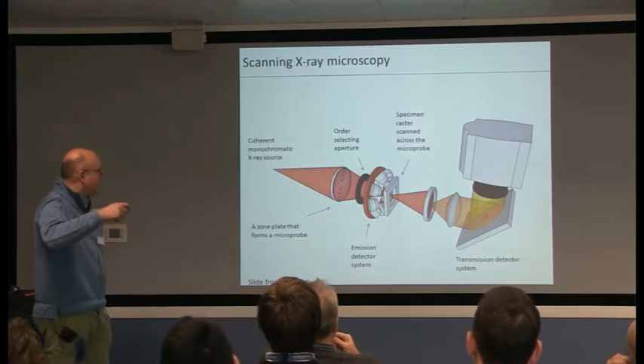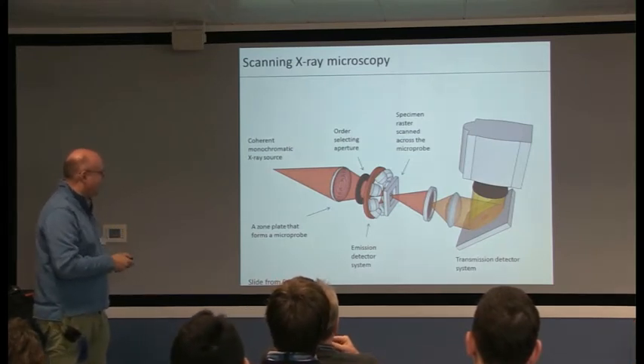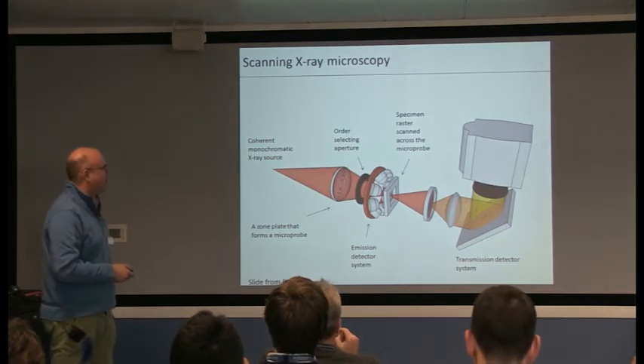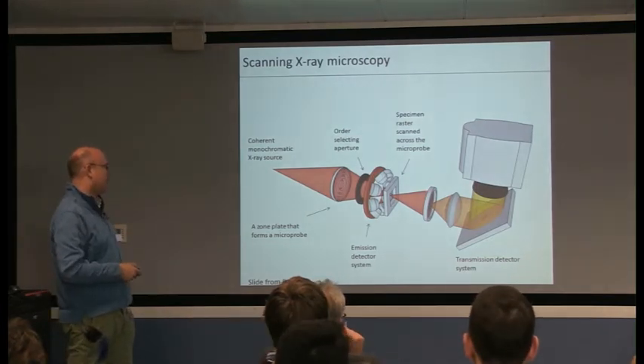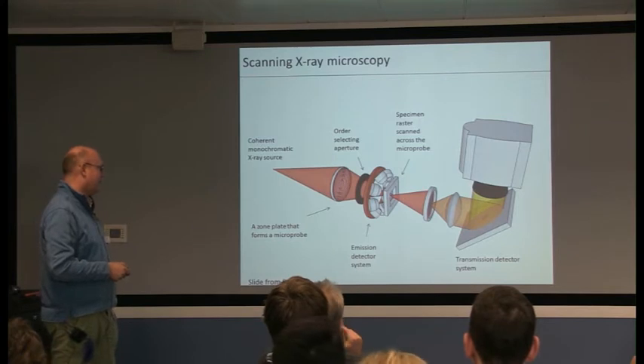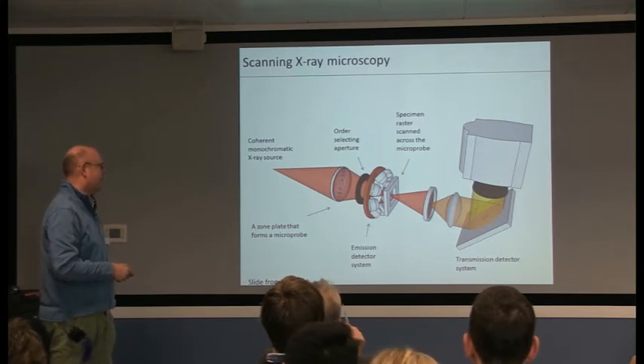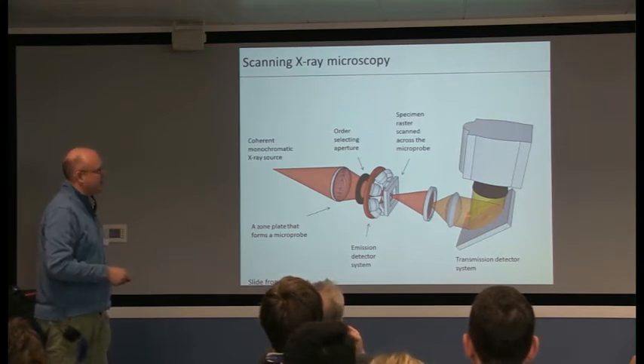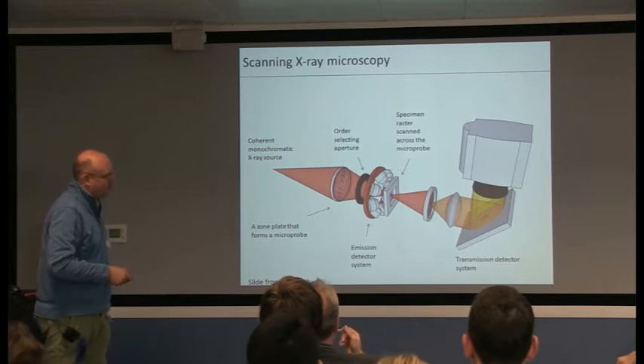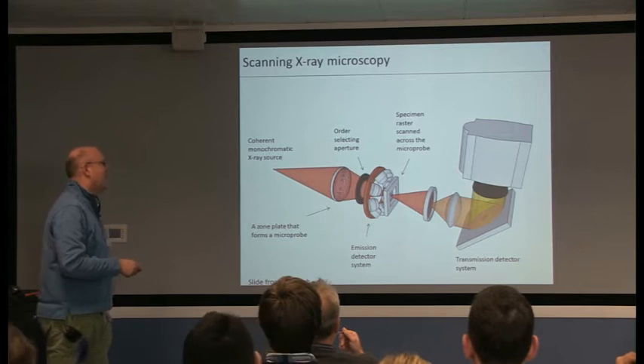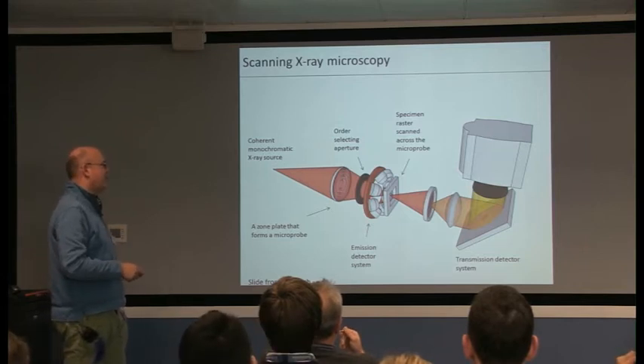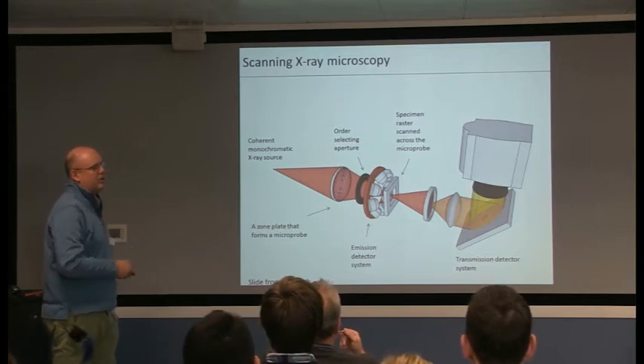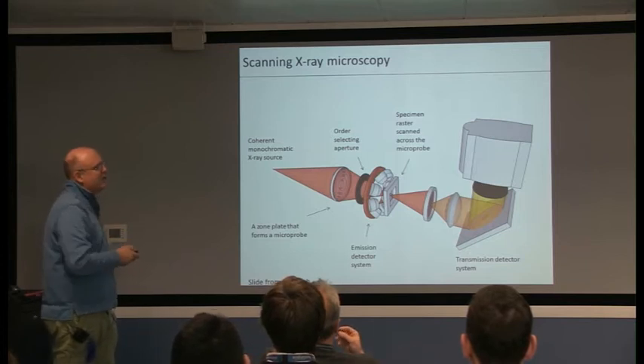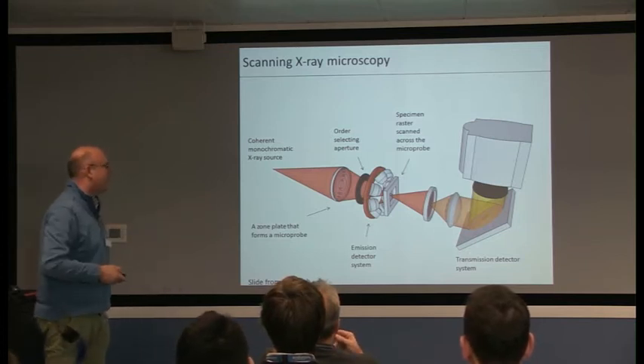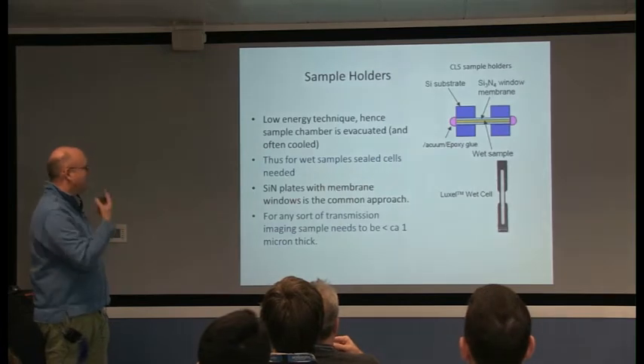Scanning X-ray microscopy - this is nanoprobe work on I-08, involving zone plates. We were using mirrors before, and you move the sample in front of the beam. These are the fluorescence detectors, and then you can detect in transmission where you get both phase contrast and absorption information, and collect the fluorescent signal. You map the sample, move the energy, map the sample, move the energy, and build up a stack of XANES scans by plotting through your energy axis, your third axis.